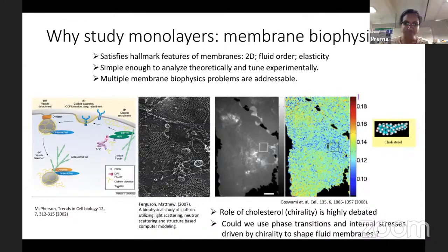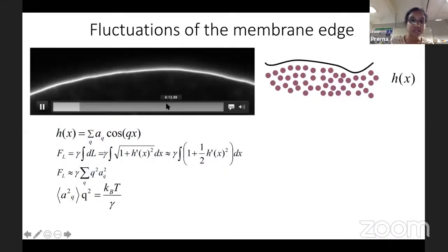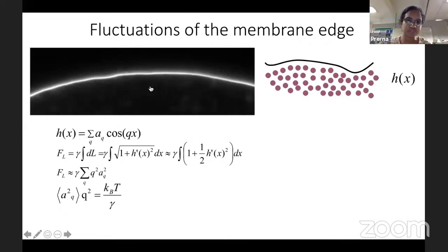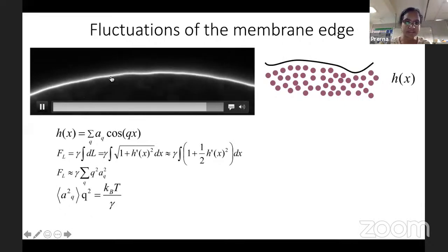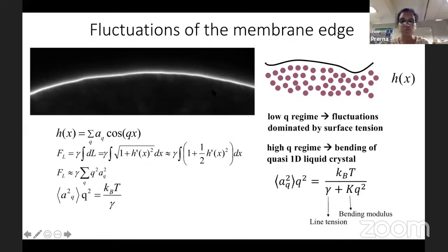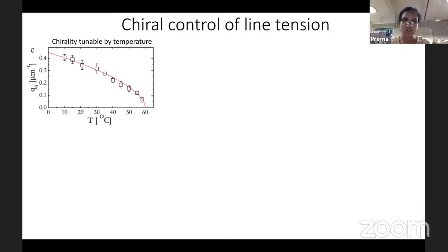I will spend another 5 to 10 minutes giving you examples and quickly going through them because I don't have much time left to give you a flavor of what we've been doing. Here you can visualize the edge of the colloidal membrane and you find that this edge fluctuates. Remember, all of these are Brownian objects, and so thermal fluctuations are good enough to cause them to move. By analyzing these fluctuations, you can calculate what is called the line tension. Remember, for 3D droplets, we were looking at surface tension. For these 2D droplets, we get what is called line tension. Now I'll show you an example of how you can control the line tension. As I mentioned, these viruses are chiral in nature.